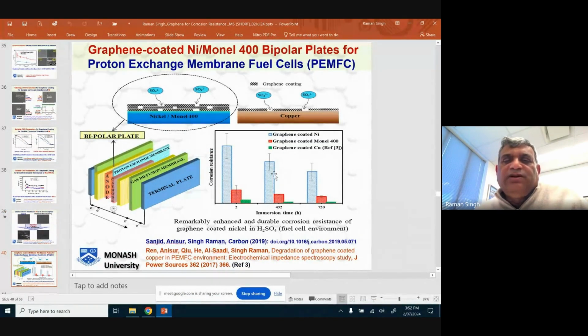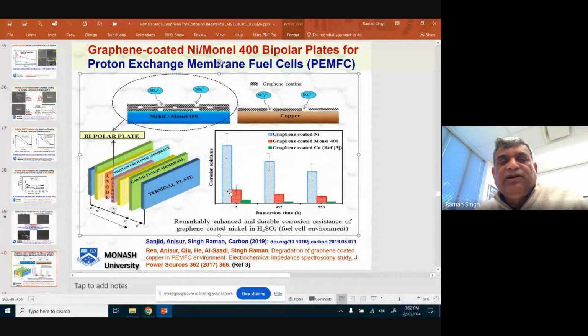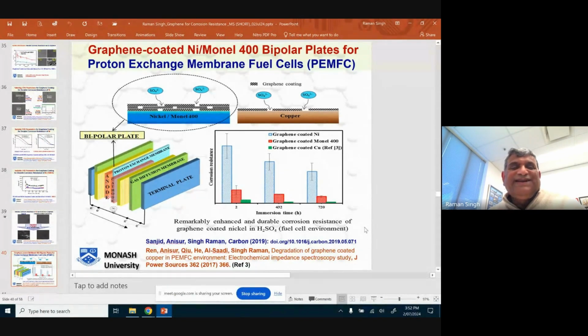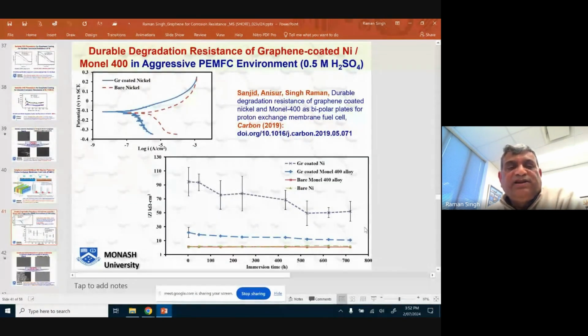And I talked to you about the bipolar plate and the use of graphene coating. We first worked on copper, that was earlier, and we published in a journal, again a good quality journal. But later on, we started to work on pure nickel, and that gave very good corrosion resistance, much better than Monel, which is an alloy of nickel and copper. So graphene-coated pure nickel gave very good corrosion resistance. And as I said, it is very useful because it not only gives corrosion resistance, but graphene is also conducting, which is one of the characteristics required for bipolar plate application.